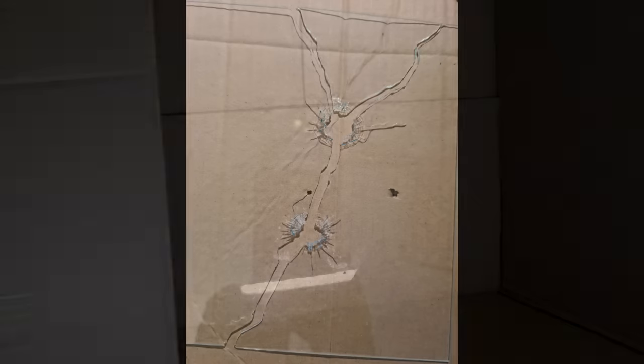And it gets worse, because if we shoot the same plate a second time, and let's face it, ships had lots of guns, another hole is punched, but then there is a complete cascade failure of the plate, and down it goes. This is very, very bad, because if we shot the cardboard twice, there would be two small holes in the cardboard. It's not ideal for the people immediately behind that, but the rest of the ship is substantially intact. Whereas in this case, our armor plating, which, bear in mind, protected us completely against the lower velocity, slightly softer projectiles, whereas our softer, more ductile material did not, has now failed so catastrophically that our whole area of our ship is now open to pretty much anything you want to throw at it.